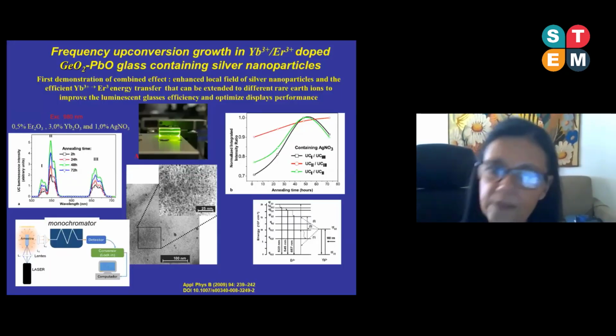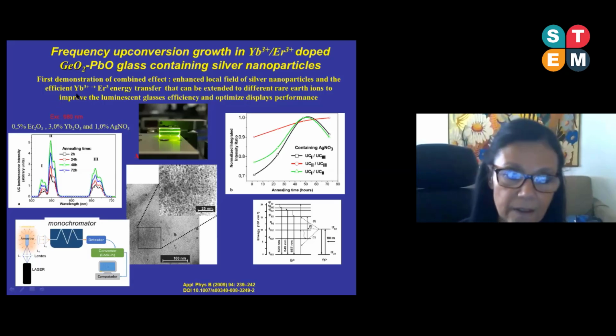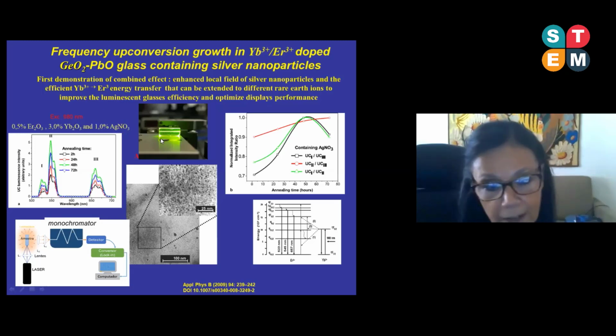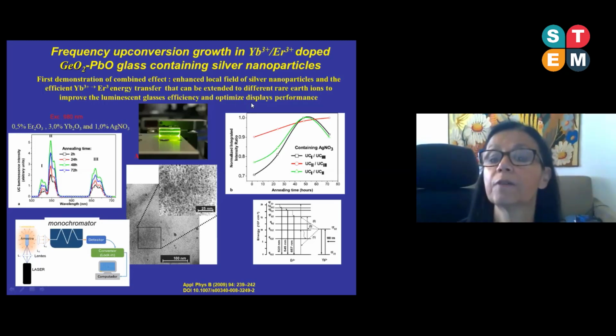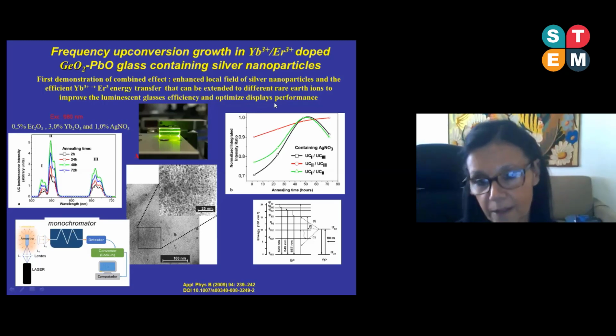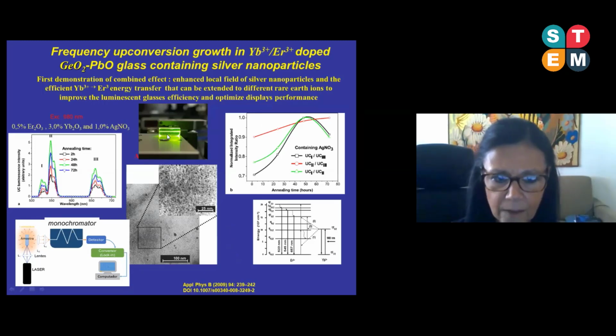Now some of the results obtained with this material are mentioned. This was the first demonstration of the combined effect of the enhanced local field of silver nanoparticles and the efficient energy transfer between ytterbium and erbium ions that provided the strong green light. This procedure can be extended to different rare earth ions to improve the luminescence glasses efficiency and optimize display's performance. And this was reported some time ago, as can be seen here.